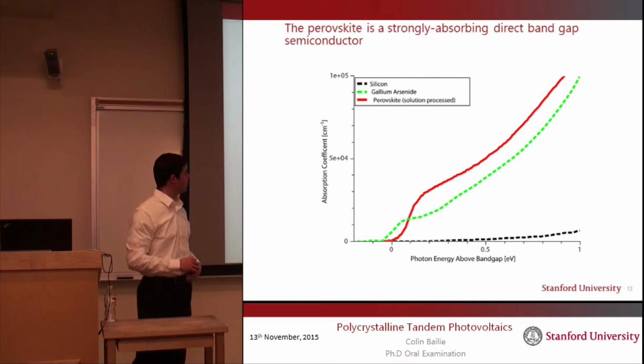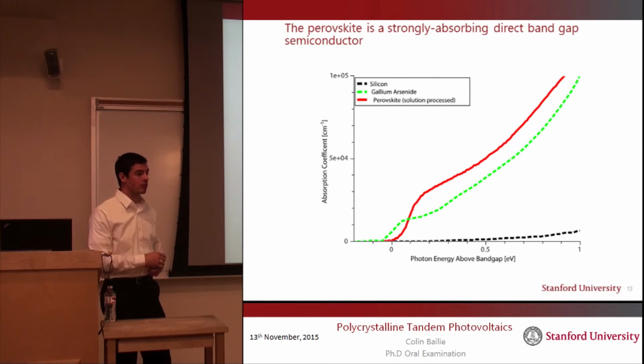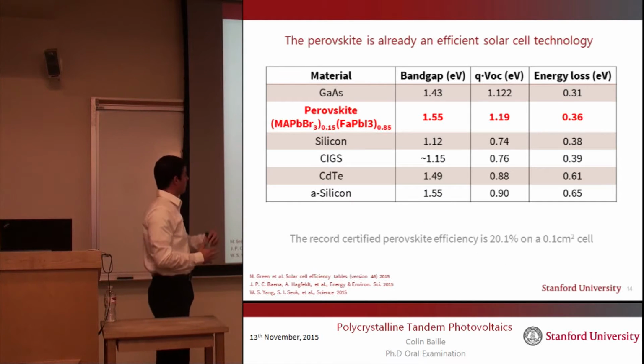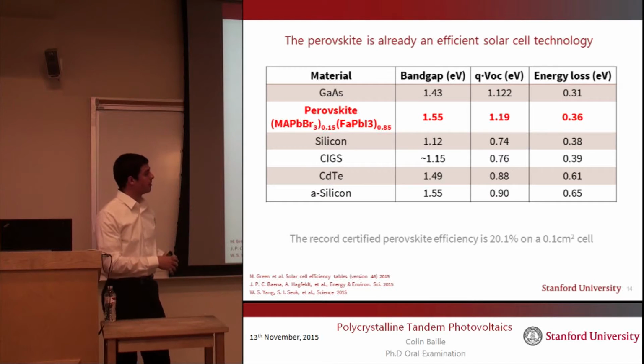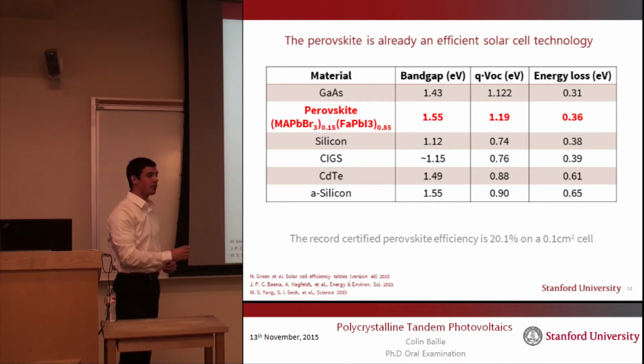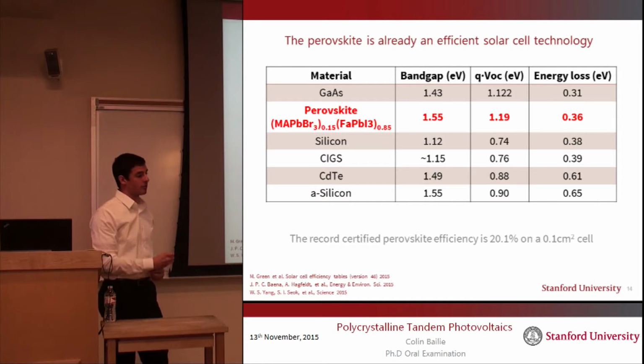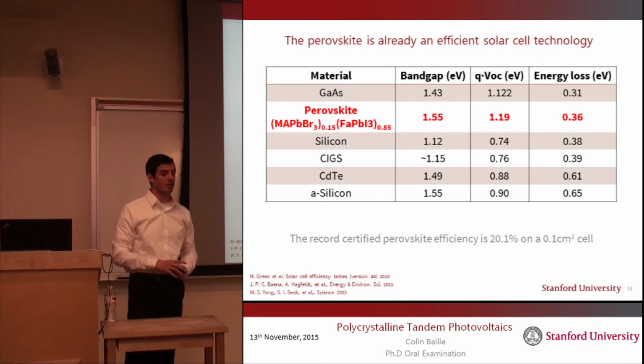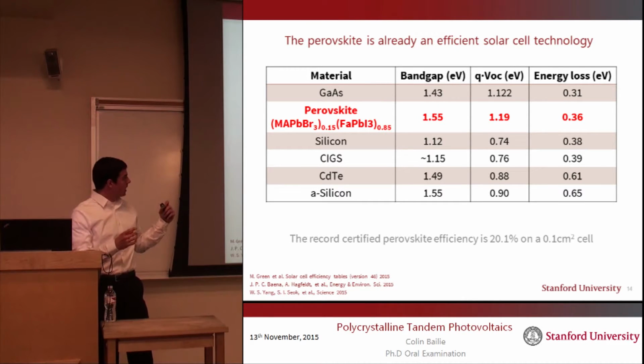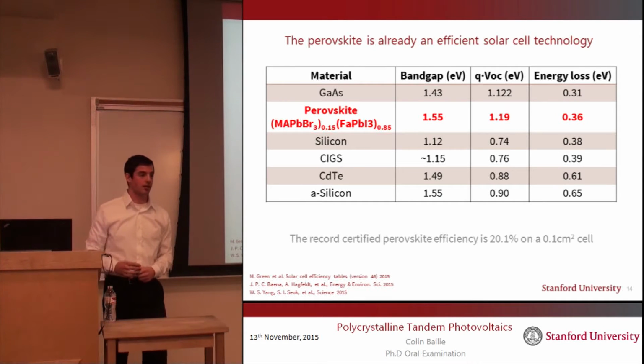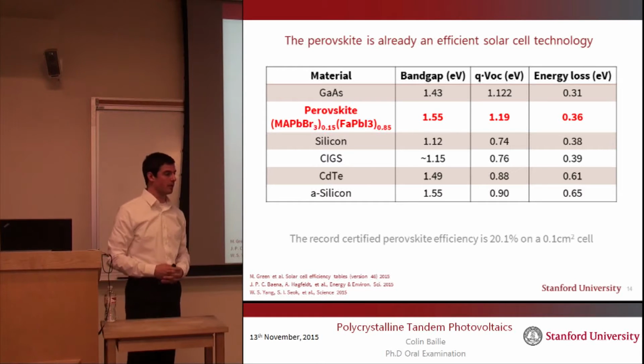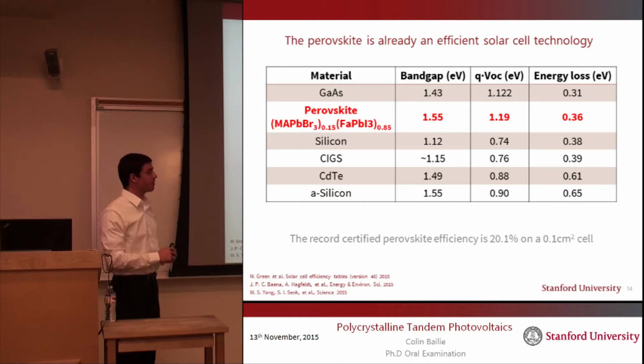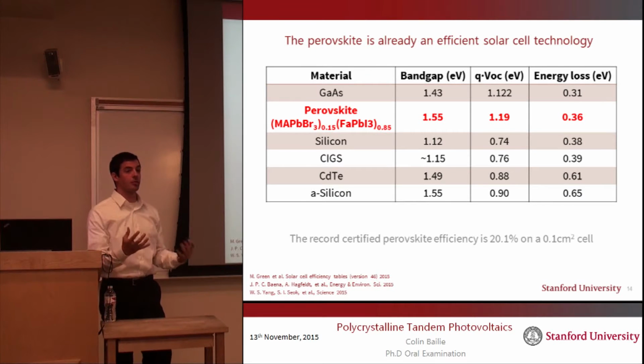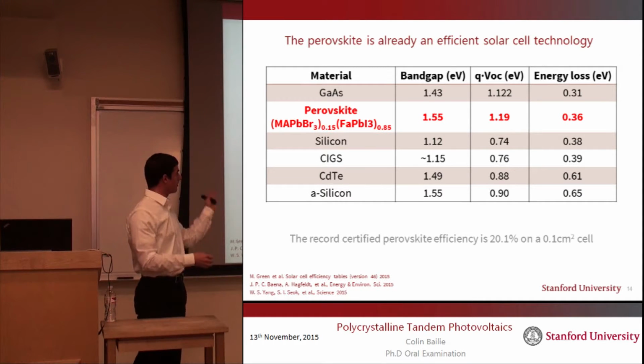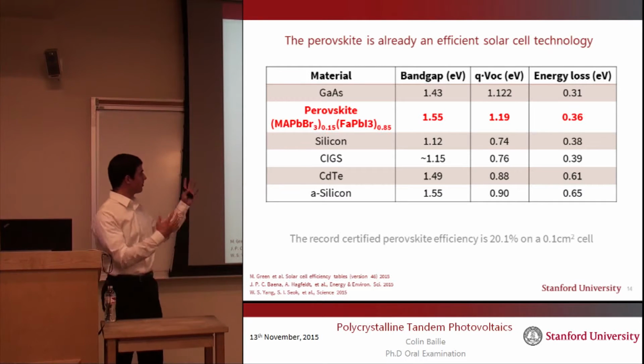First, it was a very strongly absorbing direct bandgap semiconductor, even more strongly absorbing than gallium arsenide. And it also made efficient devices. So this top chart is a table listing the optical bandgap of your absorber material and the open circuit voltage times the elementary charge that you can extract from making a solar cell. And the difference between these can be quantified as an energy loss that is indicative of the quality of the solar cell that you're making. A couple of months ago, the perovskite jumped a couple of rungs on this ladder when the open circuit voltage for these devices improved to as high as 1.19 volts, putting it past its commercial competitors like silicon, CIGS, and